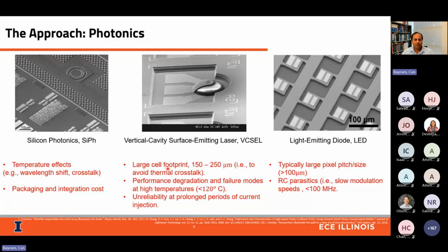Because of the heating of the element and to avoid thermal crosstalk, they are basically separated further and further. And because of the material choice, typically arsenide and phosphide based materials, they tend to fail at relatively lower temperatures than what other materials can offer, such as gallium nitride, which I will focus on. And very recently, light emitting diodes, because of their scalability and their current use and technology development in general lighting, have become an interesting point.